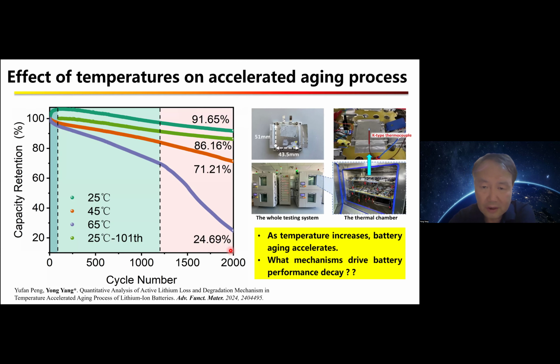I show here that at different temperatures, the capacity decay of the battery exhibits different behavior. At room temperature, 25 degrees C, it decays quite linearly. But if you increase the temperature to 45 degrees C, you can see it decreases faster, but also changes a little at some point during cycling, especially for the higher temperature such as 65 degrees - that decays faster, but strangely we can even see jump behavior at the end of the cycling.